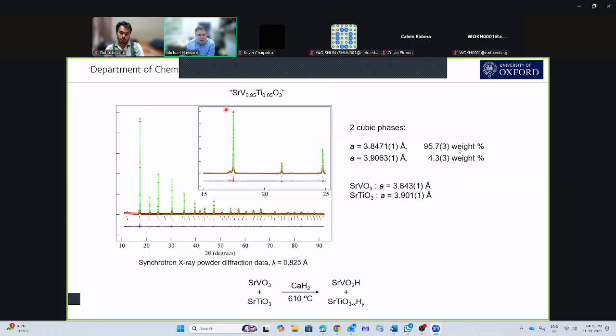So if I basically try and make a 5% substituted version of SrVO3 by the route I said before, and I again take a synchrotron X-ray powder diffraction pattern of the product, what I can see is there's a second set of peaks here marked in red. So we've got a second cubic material, and we can look at the lattice parameters of the majority cubic material and the secondary cubic material, and then compare them to the lattice parameters of SrVO3 and SrTiO3, and we can see they're an exact match.